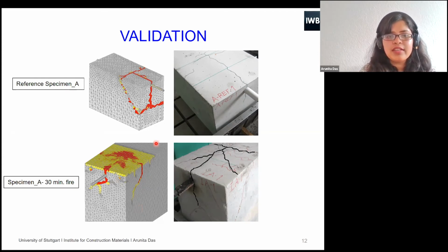Here you can see the validation with experiment. These are the numerical models. These are the experimental results. So at the back, there is a transverse crack. First, this crack appears due to the concrete tension failure, and slowly a longitudinal crack comes. All the investigated parameters, all the specimens failed in splitting failure. We can see that in all the specimens we are getting a longitudinal splitting crack.